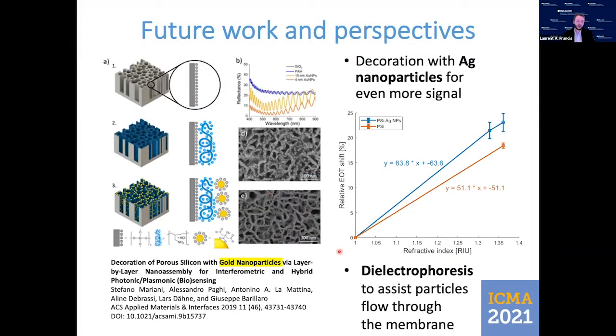For future work and for the perspective, we have the possibility to further enhance the signal, for instance, by nanoparticle decoration of the porous silicon material, for instance, by gold. It has been reported in literature for other applications, or also with silver nanoparticles, where we have preliminary results here showing a slight increase of the signal. And we can also try to push the material further inside the pores and keep them in place, for instance, by using dielectrophoresis in order to assist the particle flow through the membrane.